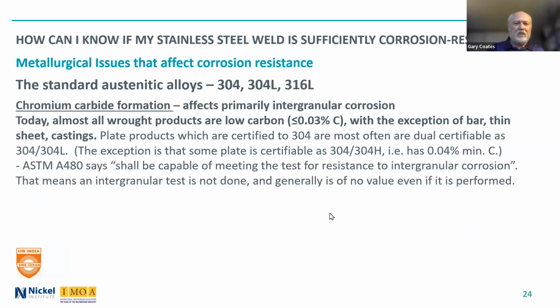So most of us in school or somewhere along the line have learned all about chromium carbide formation. Sensitization is another word for that, which affects intergranular corrosion primarily. Today, almost all wrought products are low carbon, less than 0.03% carbon. Few exceptions: bar, thin sheet, castings may not be. But plate products that are certified to 304 are most often dual certifiable as the L grade. And the exception, of course, is some plate that is certifiable as 304, 304H, H meaning that it has a minimum of 0.04% carbon.